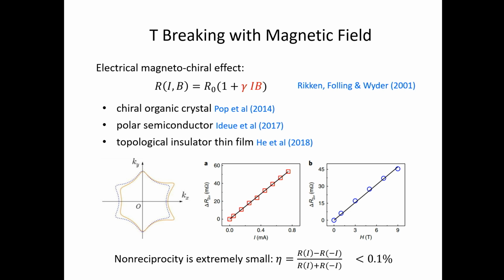Experimentally, this non-reciprocal component in the IV curve has been observed. A second order correction to the IV curve has been observed. However, this non-reciprocal effect is extremely small. If you look at the difference of the resistance under opposite currents divided by the average resistance, this dimensionless quantity is less than one part per thousand. An extremely tiny effect. This is kind of expected because the time reversal symmetry breaking comes from the magnetic field. The Zeeman energy is a small energy compared to the kinetic energy of electrons, the Fermi energy, inside the material. So it's a small effect.